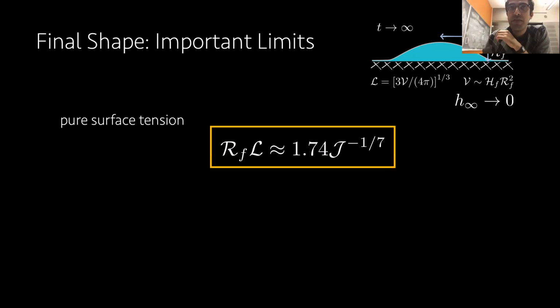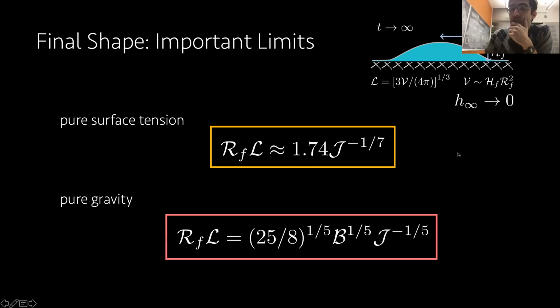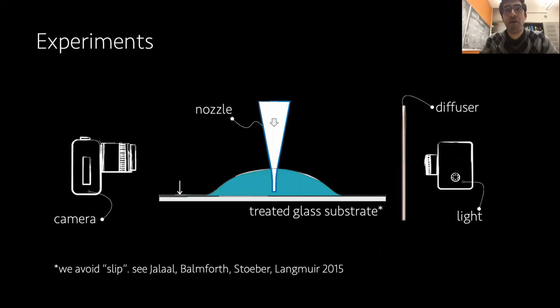Some important limits: if you have pure surface tension driven droplets and the thickness H infinity goes to 0, your prefactor is 1.74. So the prefactor is always around 2. We got lucky, it's order 1 actually. And for the gravitational case, as I said, you can find the prefactor exactly, and that's this number, 25/8 to the power of 1/5. So you now have a lookup table that is fully theoretical to find your final radius, but it was time to do experiments.